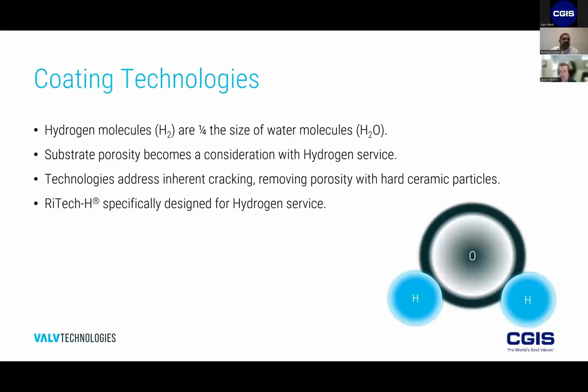And so the technology that has been developed really addresses any microcracking that could occur either in the base metals, the substrate, but also we have to remove porosity in the coatings itself. And the way that it's done is that hard ceramic particles are fired along with the coating to plug and fill any microcracking that could occur.